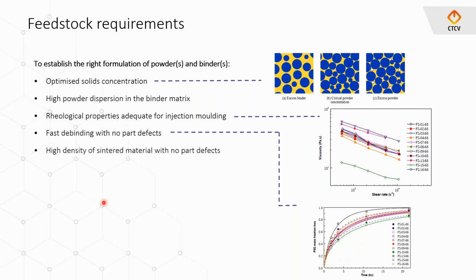And of course, we have to promote a high density of sintered material with no part defects, and the binder can be critical for this issue as well. And finally, of course, we have to achieve the right sintered material properties in order to meet the part specification.